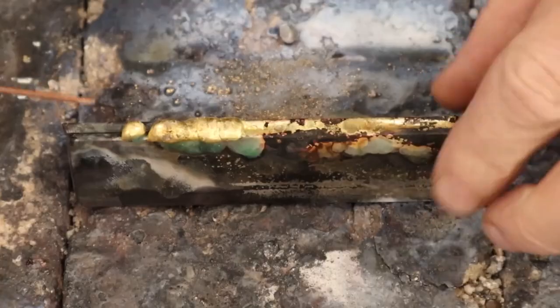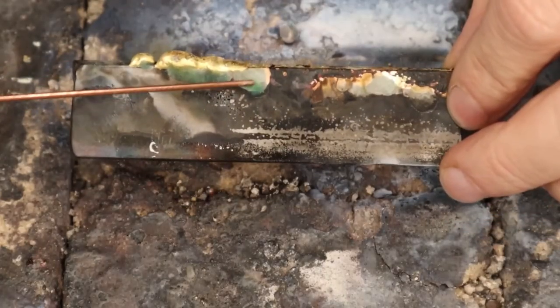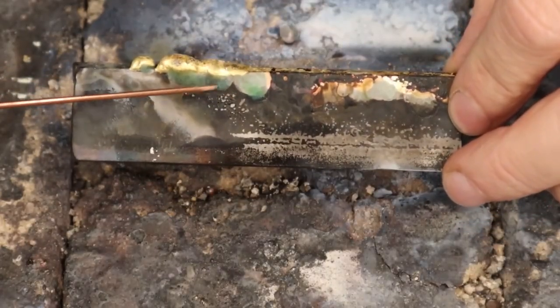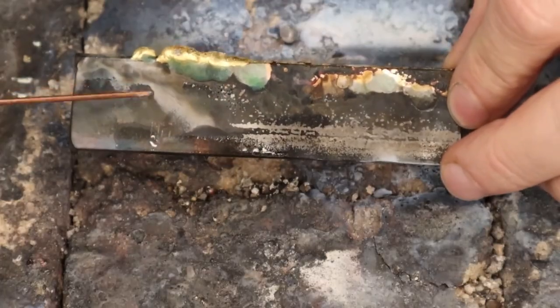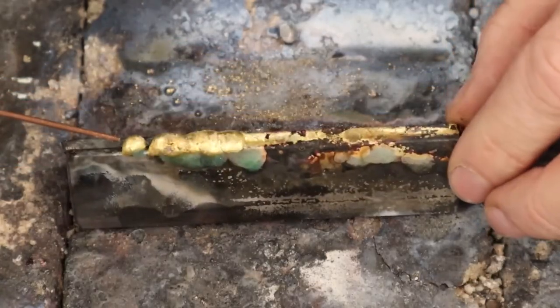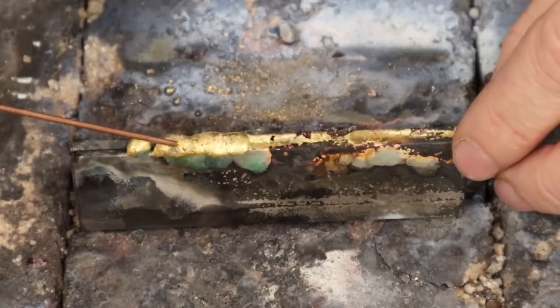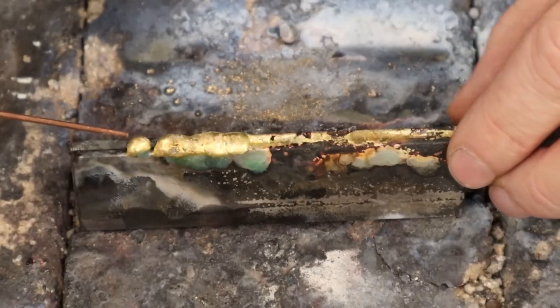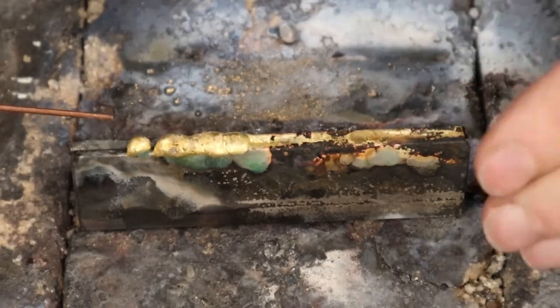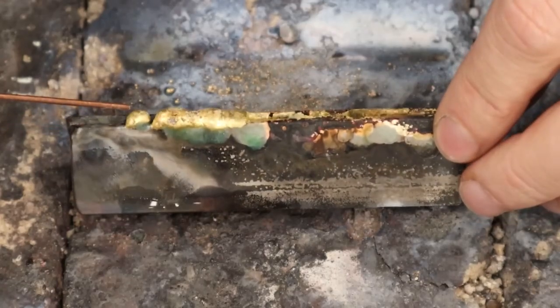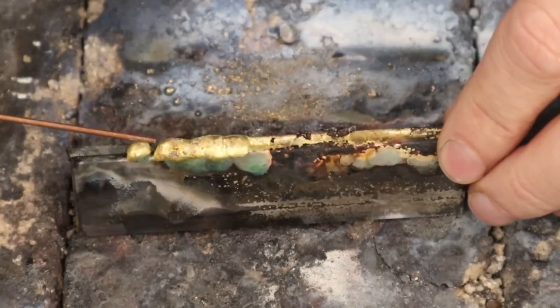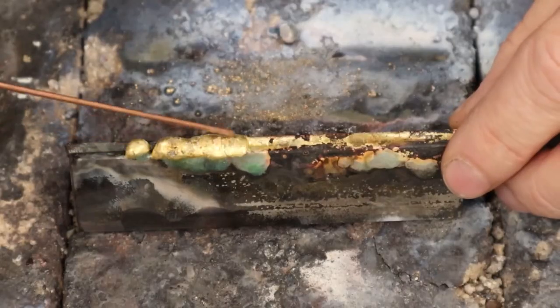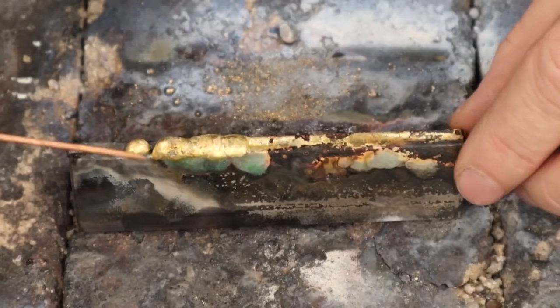You can also tell it's really cold because there's a lot of this green leftover flux that didn't actually get burnt off and didn't get activated and start cleaning the surface. Now you can look at it, it looks very lumpy, like bird poop. Should be nice and smooth, have a nice slight hump to it, or at least be flat. And in this case, it's just big bulgy pieces of poop. So really obvious, this is really quite cold.